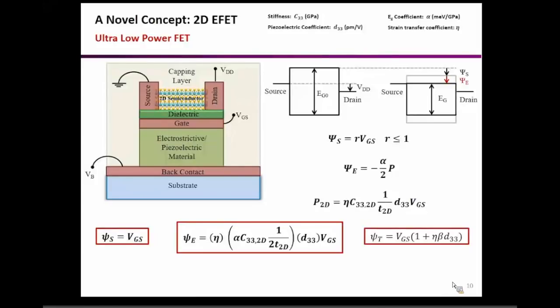So generally I think some of the calculations that one of my students, Daniel, has done, show that if you have a ratio of 1:5, then you can probably get almost like 10 to 15% strain transfer efficiency. So that will be a typical number, but those are very initial simulations. I didn't show them here because those are still at the stage of refining and we're trying to understand.